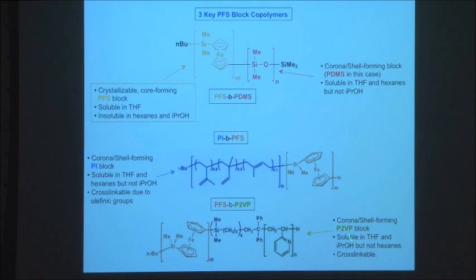And one other polymer I'll mention, this is PFS-b-poly-2-vinyl pyridine. So here you have, again, a crystallizable dimethyl PFS core-forming block. The shell will be formed by poly-2-vinyl pyridine. This is a hydrophilic block, and so this is soluble in THF, but also isopropanol, in which dimethyl PFS is insoluble. So this gives you a different type of polarity to the shell of the structure. So this is hydrophilic, whereas polyisoprene and polydimethyl siloxane are hydrophobic.